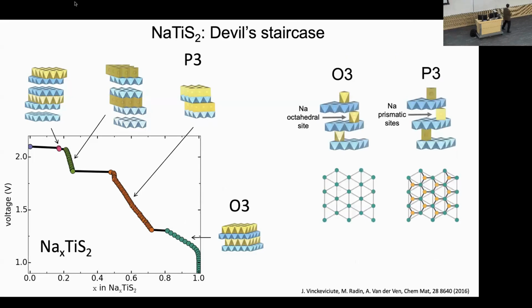But let me come back to, again, looking at the ordering tendencies within these structures. So the O3 and the P3. And it's very, very interesting. There's very interesting differences. So in the O3, if you look at the sodium layer, the sites that they can occupy form a triangular lattice. So that's the lattice in these layers. It's triangular. Whereas in this prismatic, in that case, the network of these prismatic sites, if you look at all of them together, they form a honeycomb network like this. So you have a different kind of network of sites for the sodium ions.